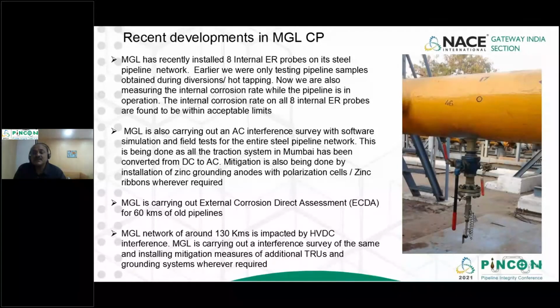Now, recent developments in MGL cathodic protection, I'll tell you, we have installed 8 internal ER probes on our steel pipeline network. Earlier we were testing pipeline samples, because we do a lot of diversions when we do a lot of hot tapping. Diversions are primarily in those areas where we have a metro, mono, and a lot of road widenings, so we need to divert our pipeline. Wherever we divert the pipeline, we take a section and send it to the labs to analyze the internal corrosion rate and what is happening to the pipeline.